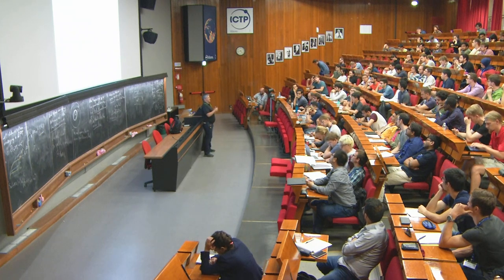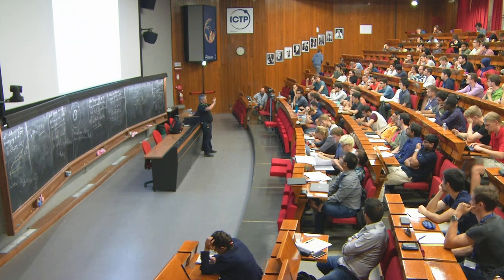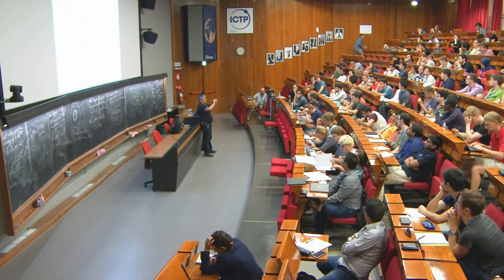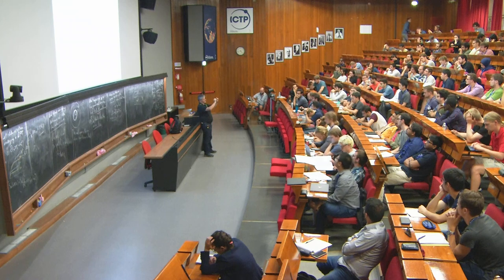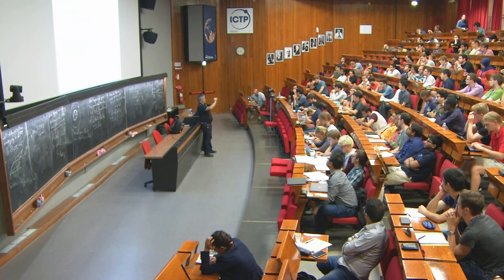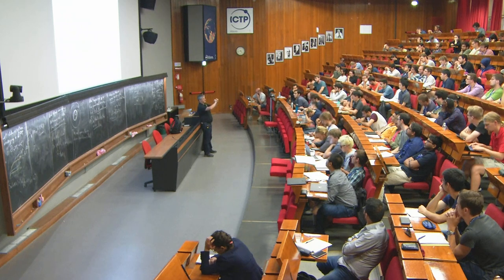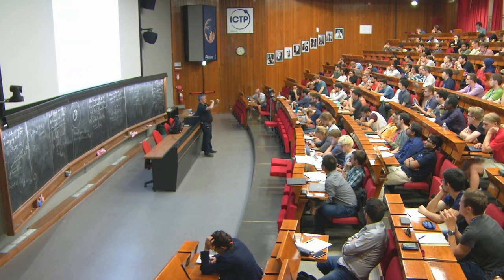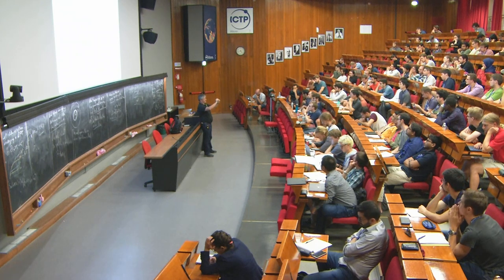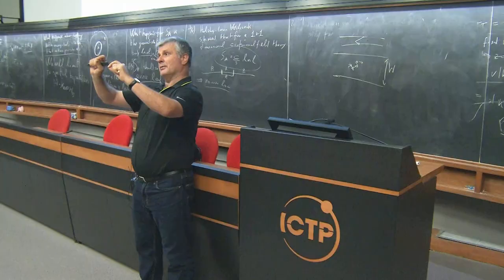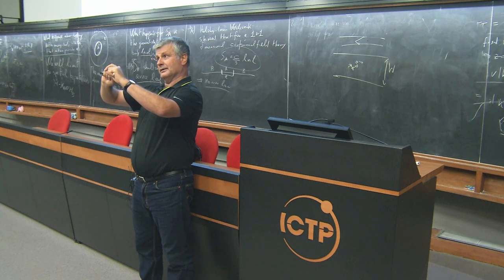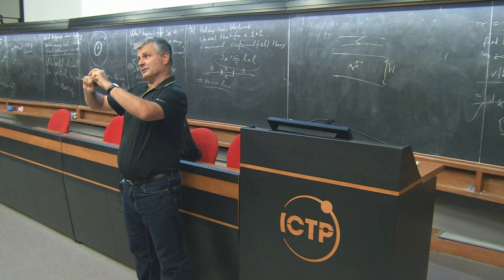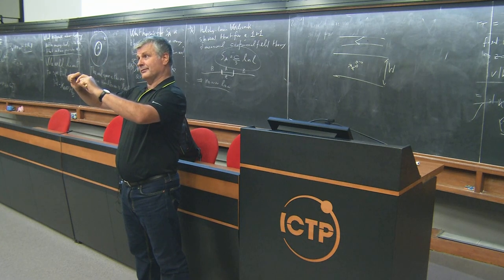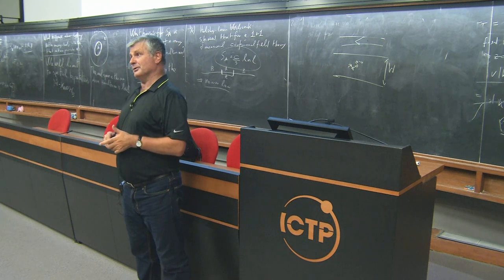Well, you could, but what you could do is even worse. You could go with the same geometry of the channel, and then you can think of what happens when an electron meets the boundary, right? And you've got two limits. In typical hydrodynamics textbooks, they use sticky boundary conditions. So they just basically say all of the x velocity is stopped when you get to the boundary, right? So the velocity is zero at the boundary. But if you had totally specular scattering, then you would have essentially no momentum dissipation at the boundary of the x momentum. So the reality is always going to be somewhere in between.